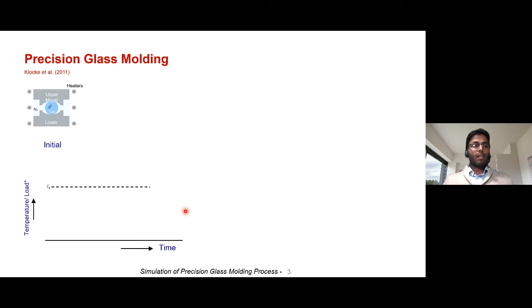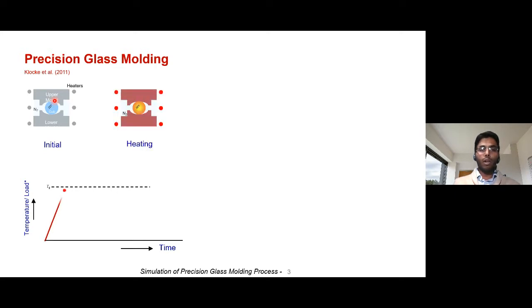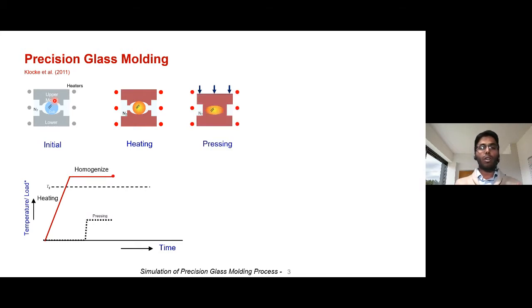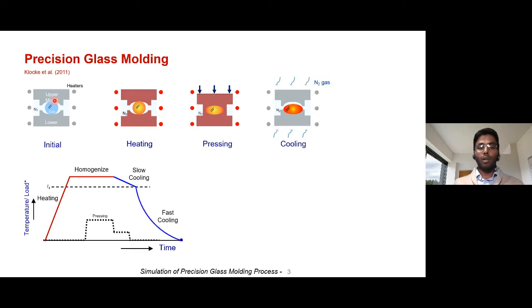Now with this, let's look into what's happening with the precision glass molding process. Here initially we place a glass gob between two molds. We have the upper mold and lower mold, and it is placed in a nitrogen environment. In this environment, we switch on the heaters, and we heat the whole assembly to slightly above the glass transition temperature of the glass material. And then we press against these molds. We keep it for some time at this hot temperature, so that there is a uniform temperature distribution. And then you cool the glass and the whole assembly by slow cooling, and subsequently by fast cooling. And at the end, you would have the lens.